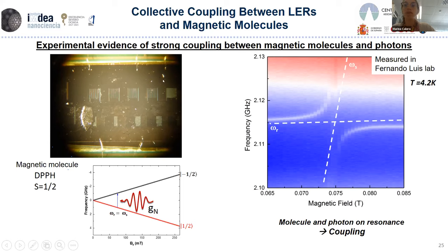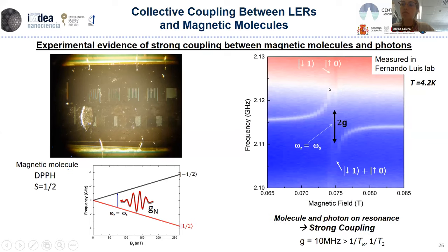So if we now measure the transmission through the chip applying external magnetic fields, we can see that when the photons in the cavity are out of resonance with the magnetic molecule's energy level, we can resolve just one transmission peak. But at a certain external magnetic field, at which the energy level of our molecule is in resonance with the energy level of the photons, we can resolve two peaks, which are related with the two new energy levels of the hybrid system.